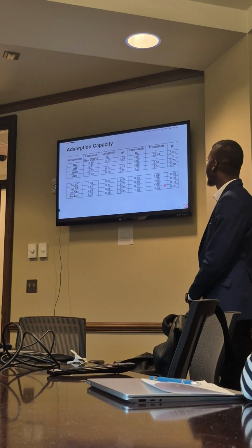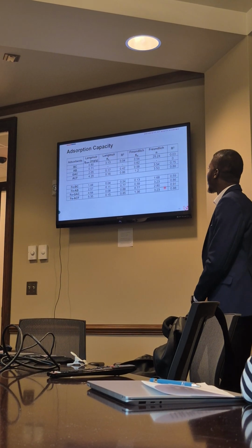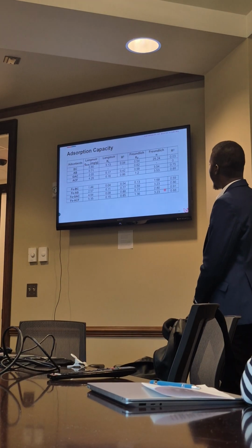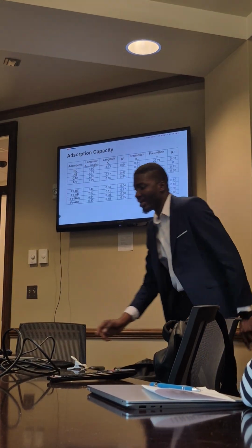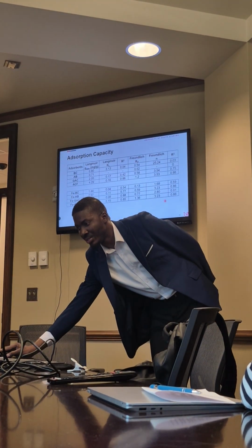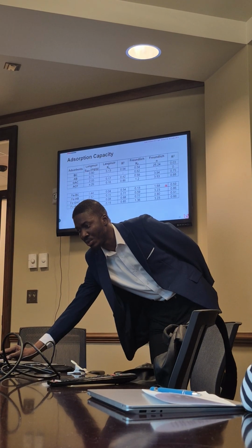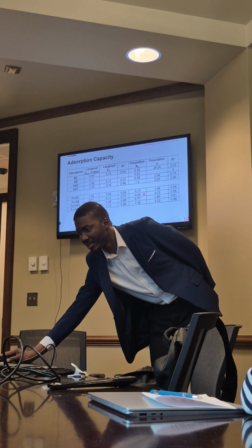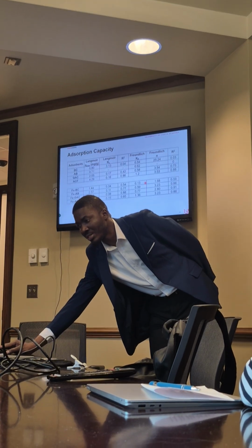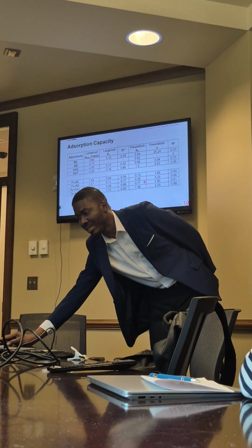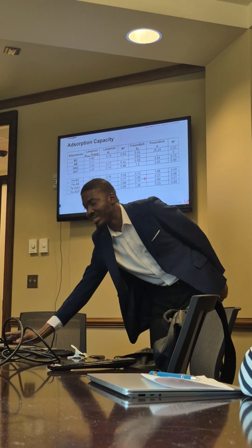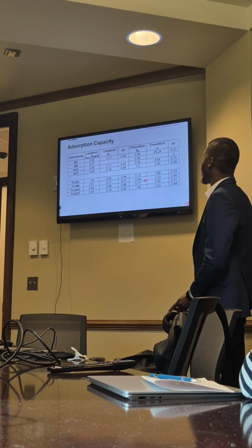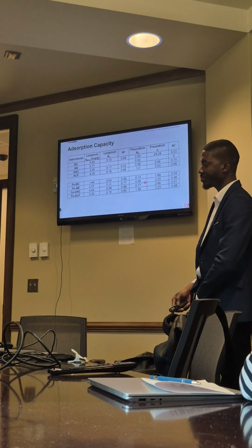of our adsorbents. Looking at our N constants for Fe, our iron modified adsorbents, we can see that they are all between 1 and 10, signifying that our adsorption process was favorable. Also looking at our Freundlich K, we can see that our K values were increasing in this order with the adsorbent, signifying increasing adsorption capacities as well.